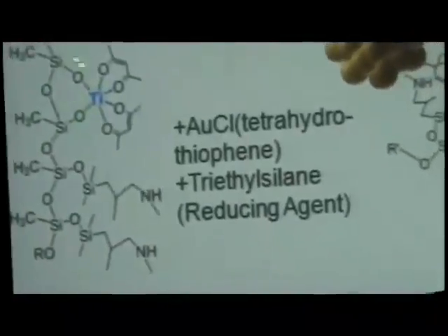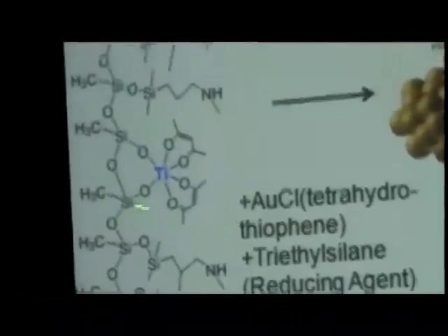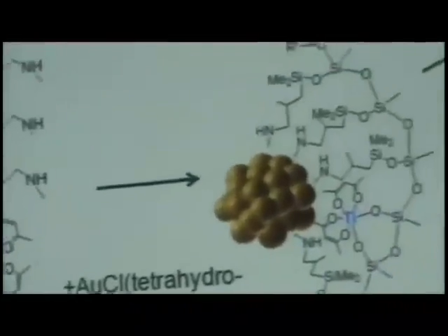We take this silane molecule, we oxidize the silane to silanol, and we react the silanol with a siloxane molecule to generate this amine ligand, or we can react it with a titanium acetylacetonate bis-isopropoxide to generate this particular titanium ligand. What's so good about this reaction?